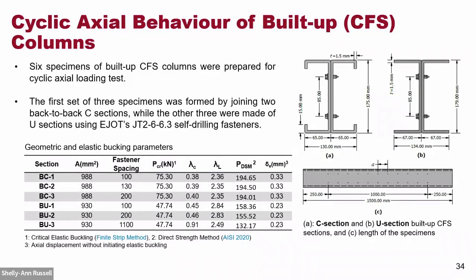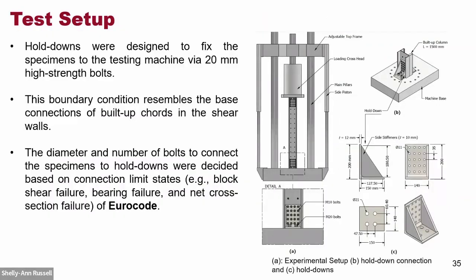And these were combined by self-drilling fasteners. The diameter was 6.3. The experimental setup that we used, you can see in this figure. We used this universal testing machine that has the capacity of applying a force of 500 kilonewtons. And we applied the actuator loading from this load cell. The specimens were attached to the machine by these hold downs, and the hold downs were connected to the base of the machine by these 20 mm high strength bolts.